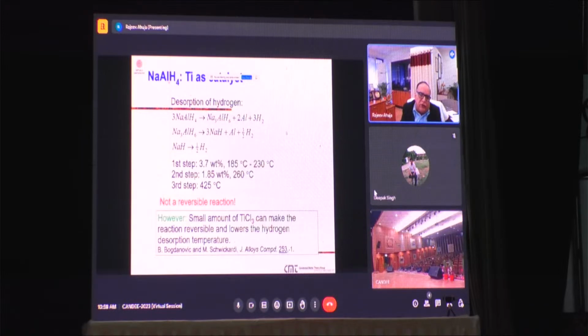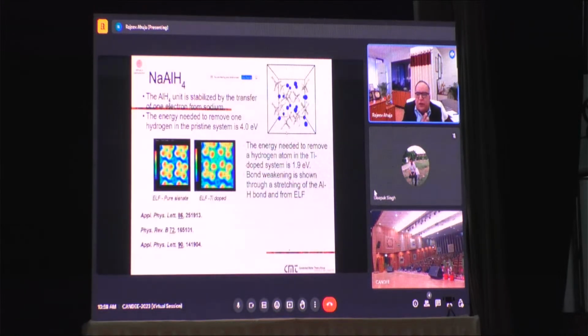So I have to reduce the desorption temperature to around 25 degrees centigrade. So we have to think about how we can do that. Then there was one experimental work where they have shown that if they add some kind of catalyst like titanium trichloride, they can make this reaction reversible and lower the hydrogen desorption temperature. So we have looked at it in the sense that if this avoids the hydrogen absorption, why can we not use other catalysts which can maybe work much better.